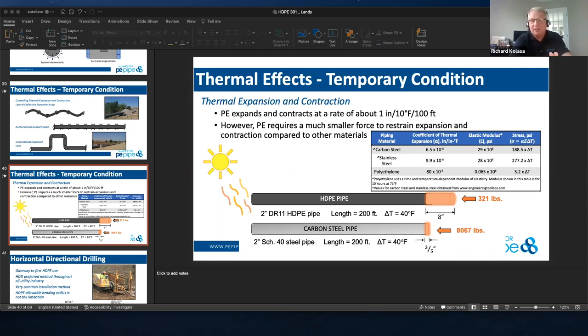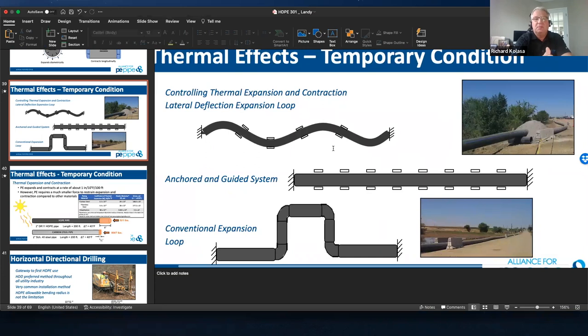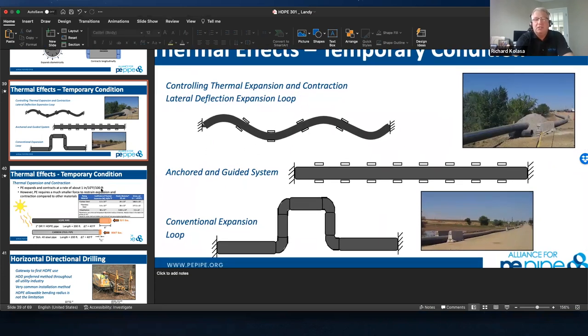You can use concrete pillars to hold it in place if you wanted to do that. Landfills use it quite a bit. They just pin it in, typically with wood stakes, and they're holding it in place. Or you can completely restrain it. You can use concrete blocks and clamps to completely restrain it if you wanted to. As soon as you narrow that distance, of course, that expansion and contraction differential will become reduced. In the top slide on the left-hand side, you can use expansion loops, like a lot of methane gathering in landfills is being used. That little U-shaped system in the bottom with the four 90s in it will take care of that expansion and contraction, and you don't have to worry about it.